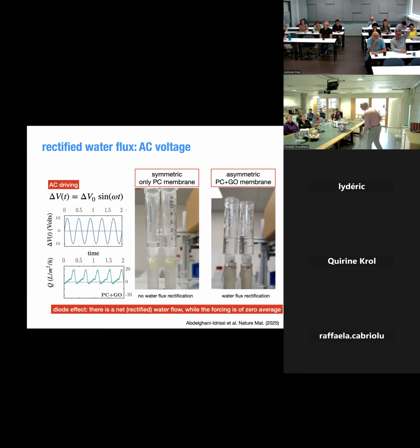But then if you start to add carbon nanotubes, graphene oxide, you see it goes to one side, stops, goes to the other side, stops, and you see rectification here. This is flux versus time, and you see that it does not go on the negative side. So you really see a rectification. And so you have a rectified water flow, an osmotic diode.